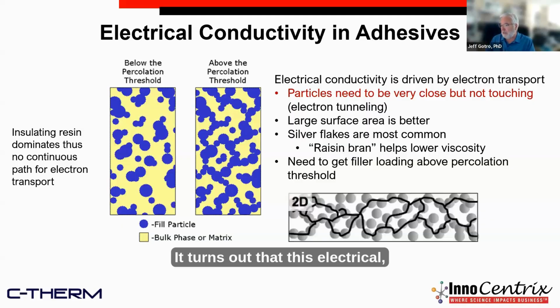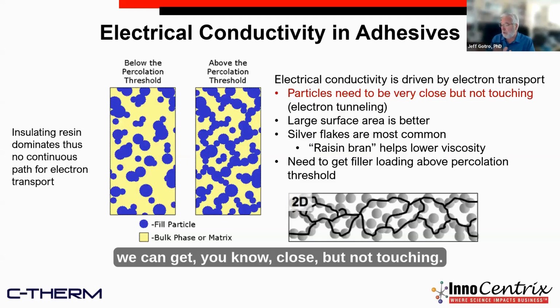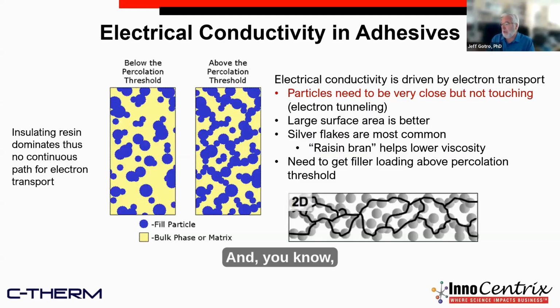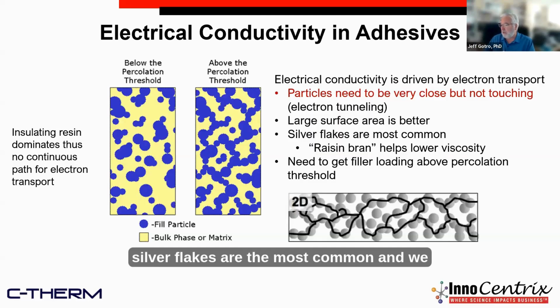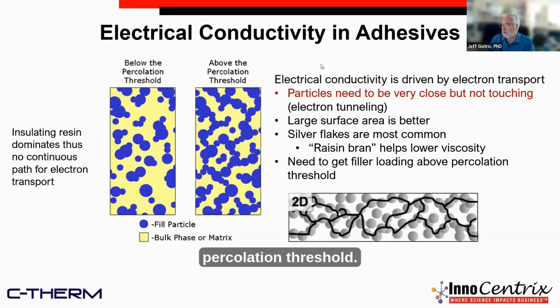It turns out that this electrical conductivity is really driven by electron tunneling. So we want large surface area so that we can get close but not touching. And silver flakes are the most common, and we need to get the filler loading above the percolation threshold.